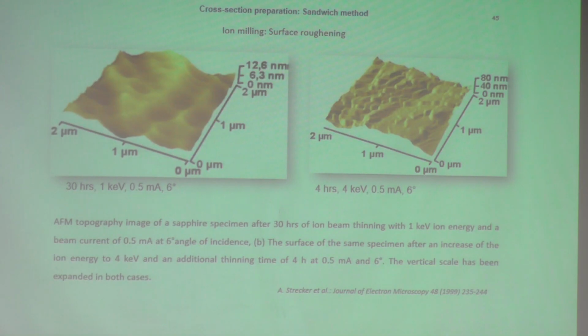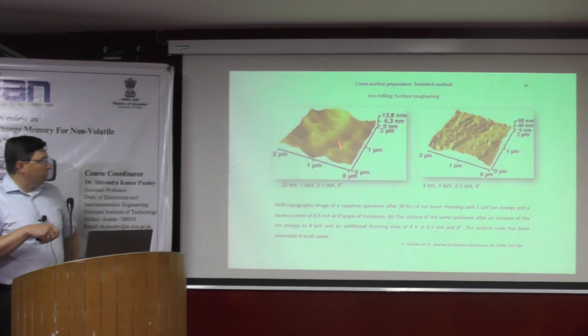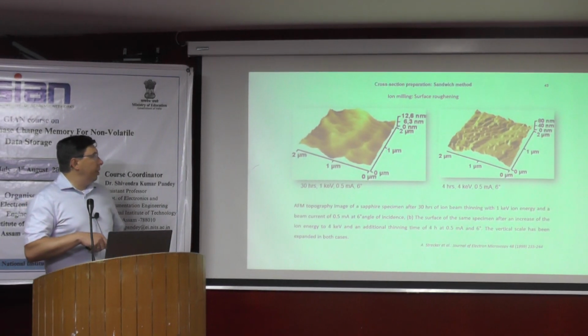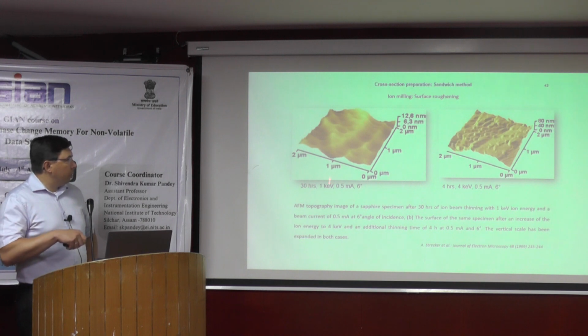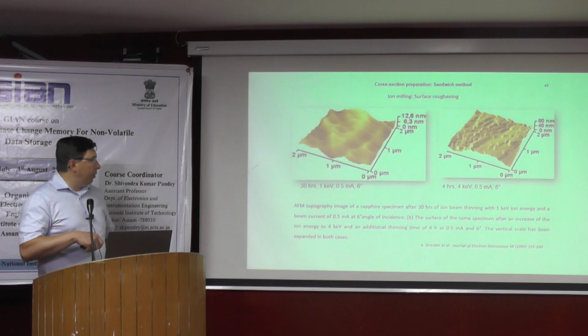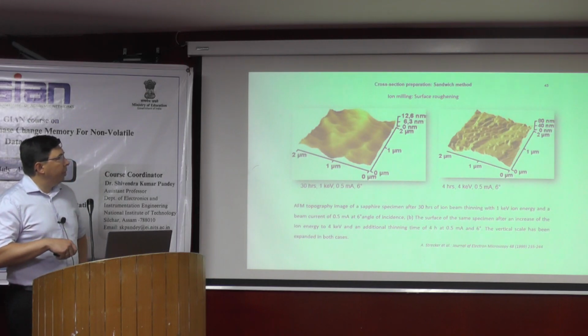This image shows you the surface topography of sapphire after ion beam thinning for 30 hours at 1 keV.